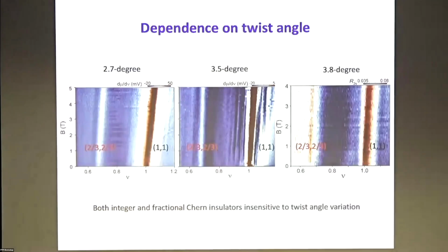Okay. And you can also do this kind of measurement on different twist angles from 2.7 degree to 3.8 degree. And basically, these states are pretty robust there. Both the 2/3 state and the filling 1 state keep being a fractional Chern insulator and a Chern insulator, with little variance in the angle.